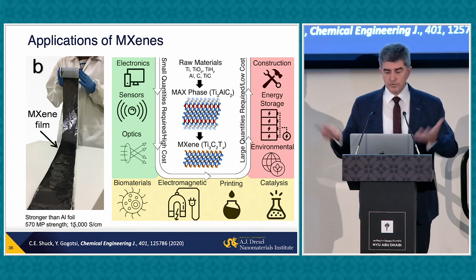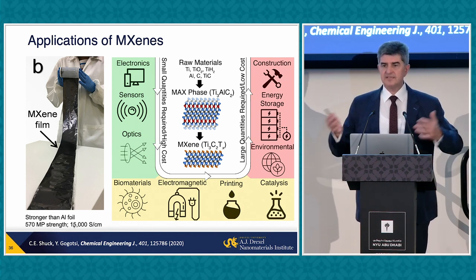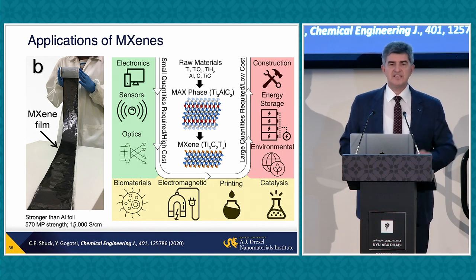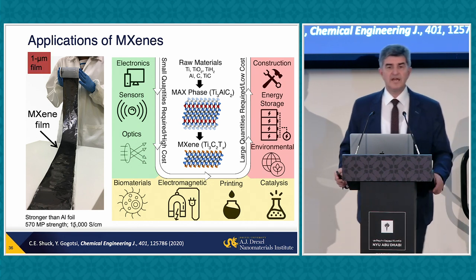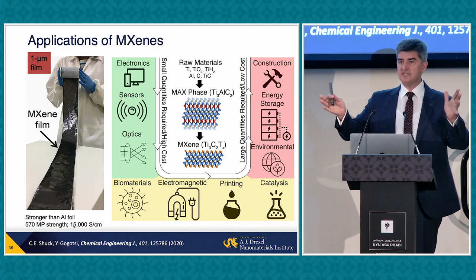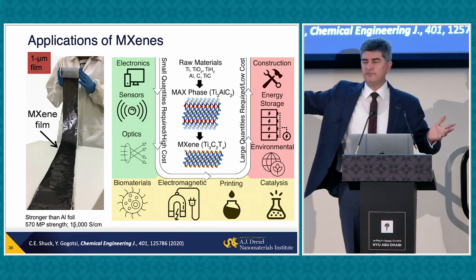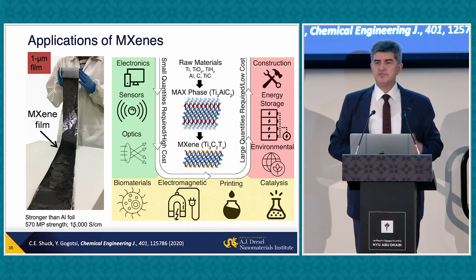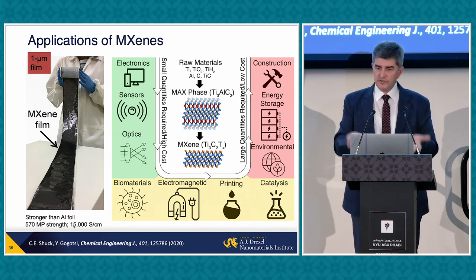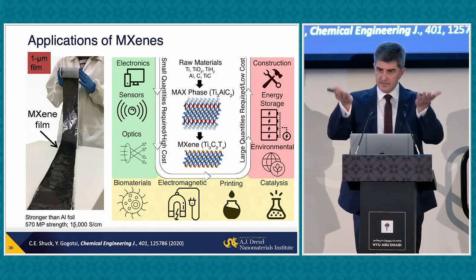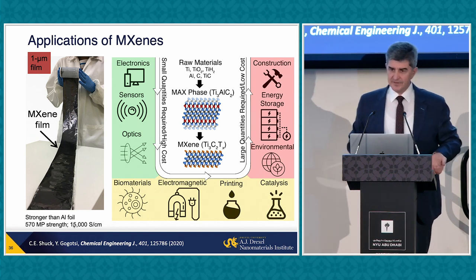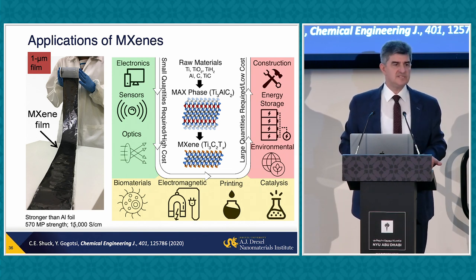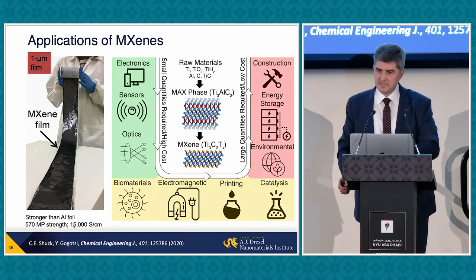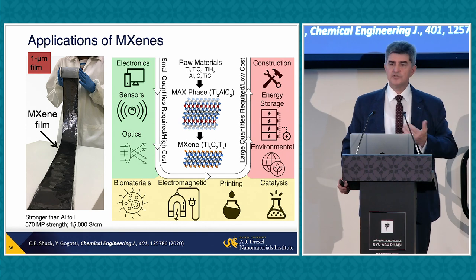We can basically go to building batteries, solar panels, other devices which require membranes for water desalination, which require a larger amount of materials. What you see here is actually a 1 micron thick film of MXene produced by taking a colloidal solution, spreading this over the surface, and drying. You get material with the strength of aluminum foil. A 1 micron film can already be handled freestanding. You can make a paper airplane out of it, but it has a conductivity of 15,000 Siemens per centimeter, 10 times larger than you would get, for example, making graphene oxide processed a similar way, heating to a few hundred degrees C to make a film.